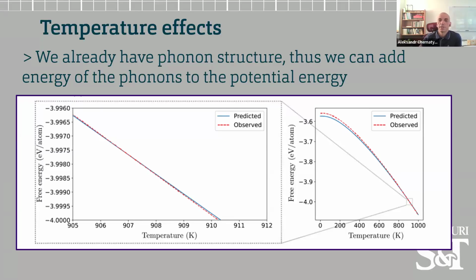So it is entirely feasible that when the solid state reaction was taking place at this elevated temperature, the system basically stayed in that lower state once it was annealed down to the lower temperature. Again, in the case of the manganese, this is not quite the case. In the manganese, these lines never cross, and so it's a good question if the different structure is still out there.